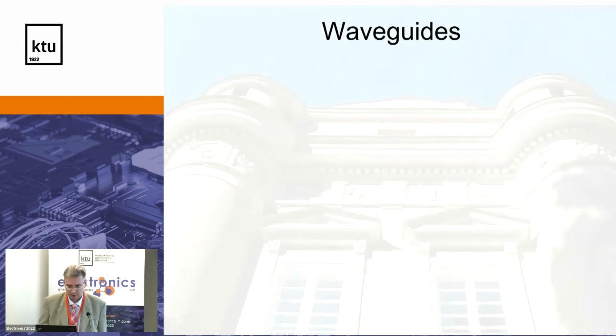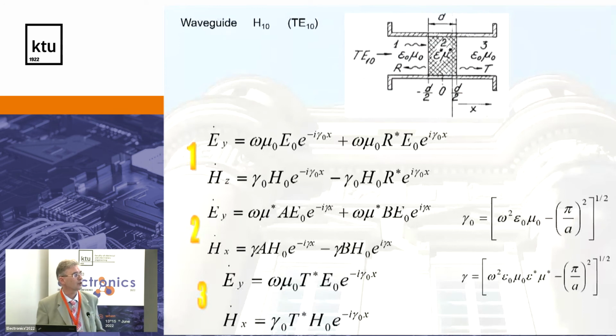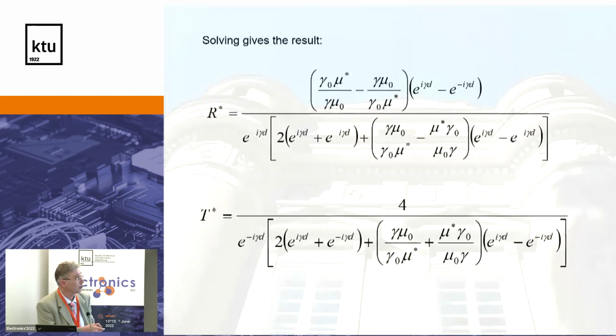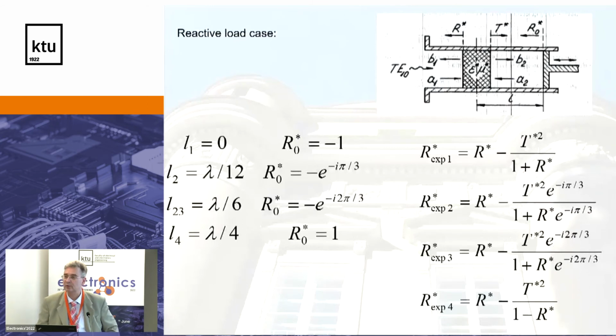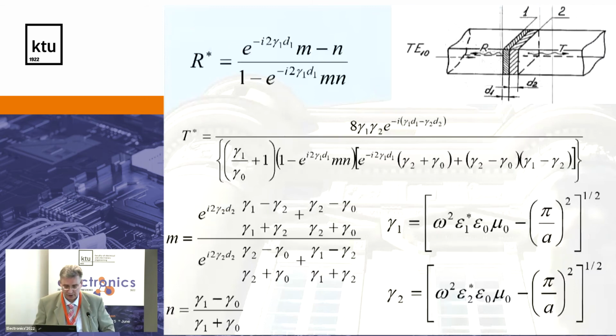Now I will tell very shortly about waveguides. What I mentioned for ferroelectric materials, if you have a fully filled cross-section, again, Maxwell equations and boundary conditions, nothing more. And electric and magnetic fields in first, in second, in the material, in third, and again, boundary conditions matching, and you can solve reflection and transmission, and from that you can calculate the electric permittivity and magnetic susceptibility. Another method which is popular is the reactive load case, where you have a short and you change the position, and in different positions you are getting different reflections, and from that you calculate the parameters of the material.